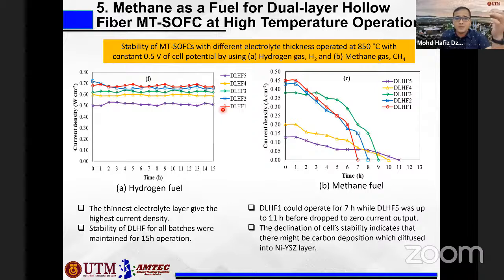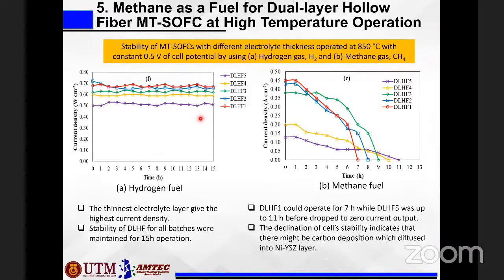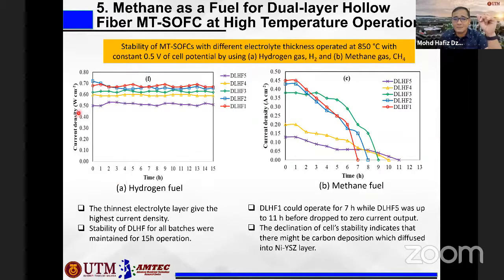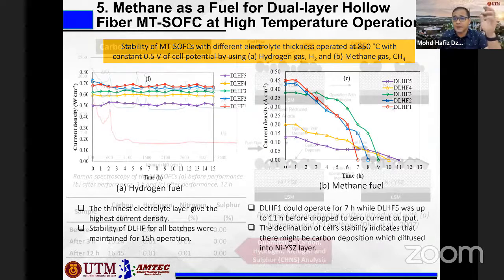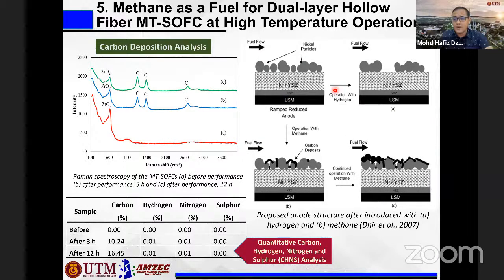For hydrogen, we can see that the cell with the thinnest electrolyte has the highest current density. The thickest electrolyte has the lowest current density, and the performance is stable throughout the time. Okay, meaning that it can operate for a longer time with hydrogen. But when you use methane as the fuel, you can see that the thinnest electrolyte has a shorter lifetime. It drops very fast, and the lifetime extends a little bit when you have a thicker electrolyte. Okay, so this is because of the carbon deposition that takes place when you have methane.